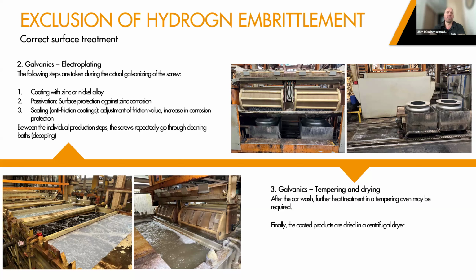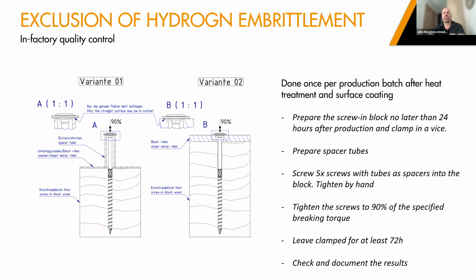After both steps you saw, the hardening as well as the surface treatment, we still do our HE testing. For the HE testing, we install the screw either into a spacer tube in a steel plate, or directly on a thicker steel plate. This is done once per each production batch after heat treatment and surface coating. This test is to be done within 24 hours after those steps.